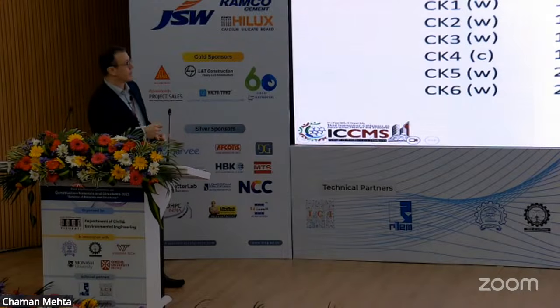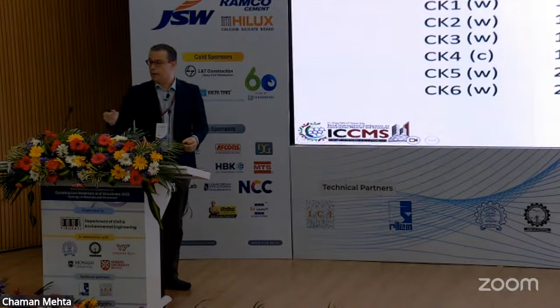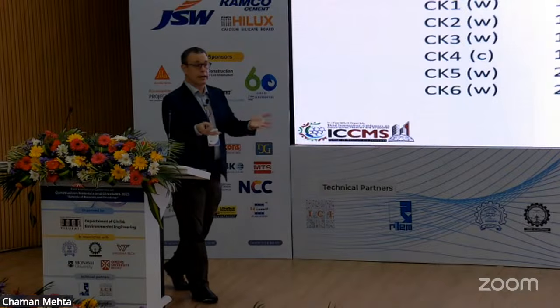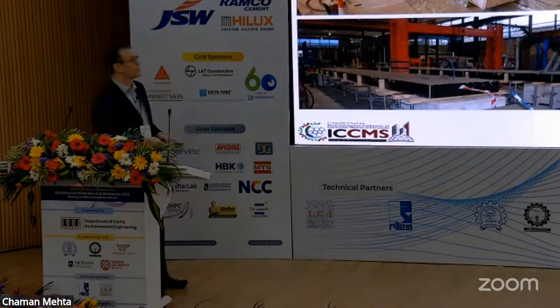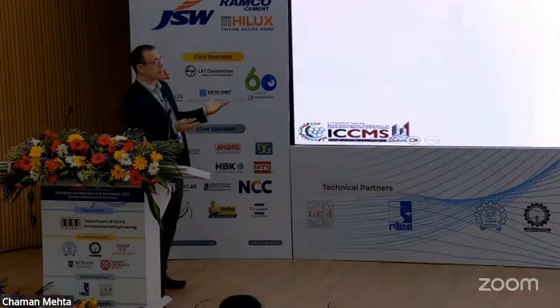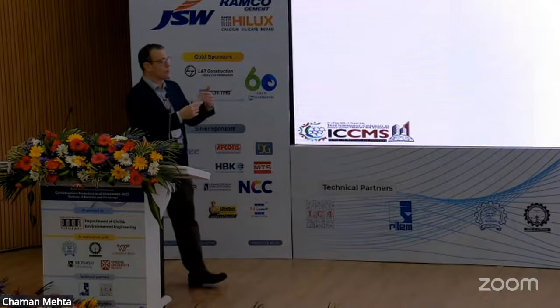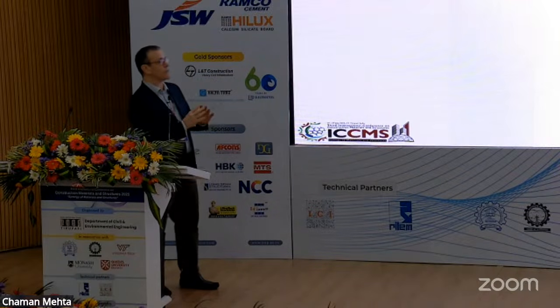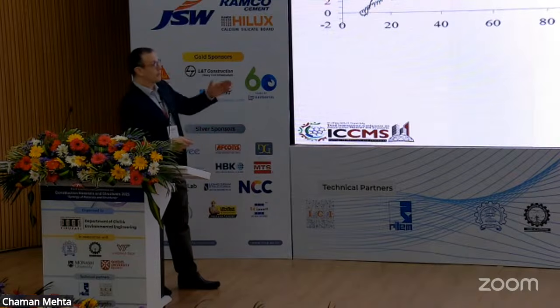We also applied other samples where, in one particular one, we put curing compound, a sort of liquid that you put on top of the slab to stop it evaporating. Here you can see some plots of the test setups, some during preparation. You can see the curing compound on the top reduces the deflection, so it's helping. But again, if you look at the data sheets, curing compounds are only viable for a maximum of a year or a couple of years, so you wouldn't want to specify this in design. How you apply them is also very variable, so it's not something you can really specify from a structural viewpoint. But it has an effect.